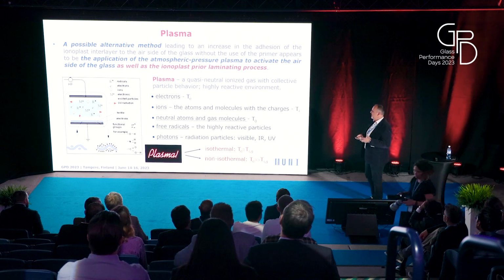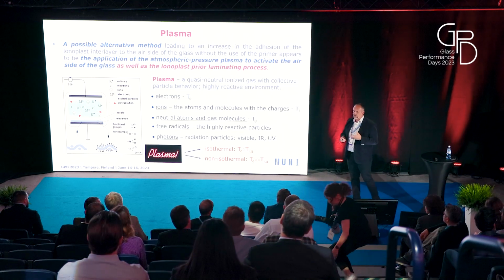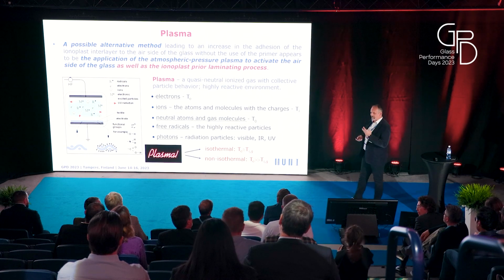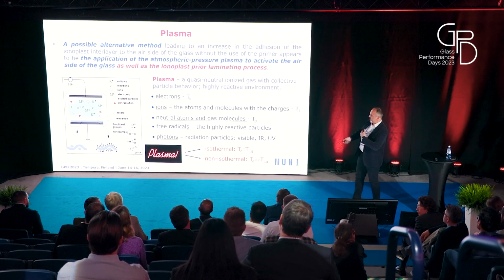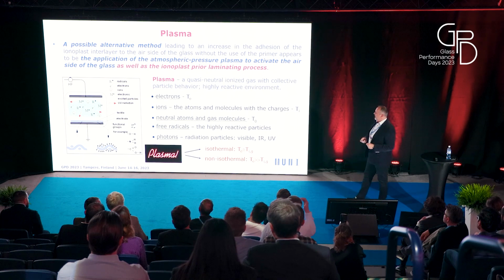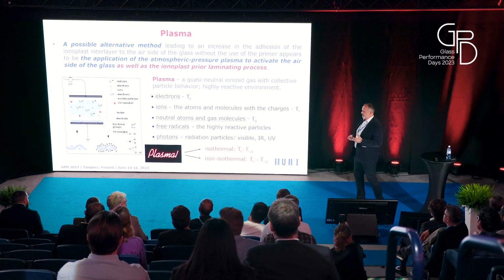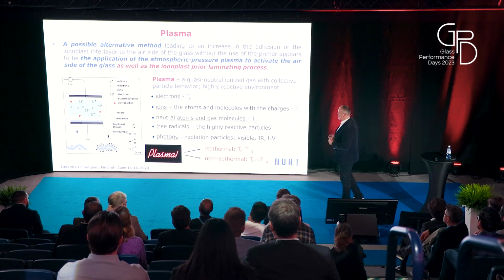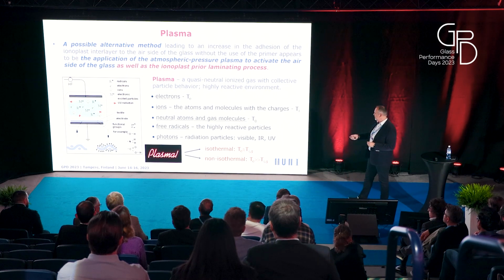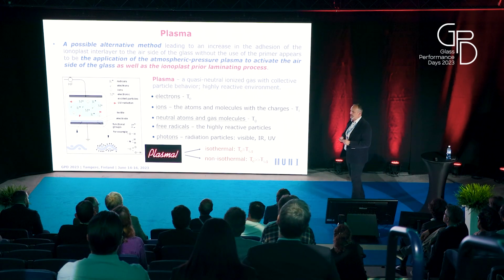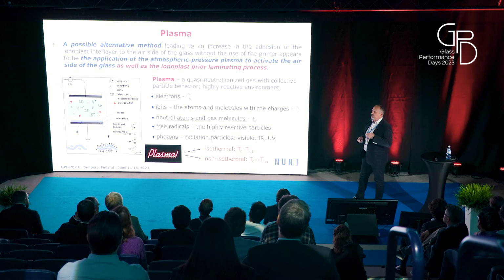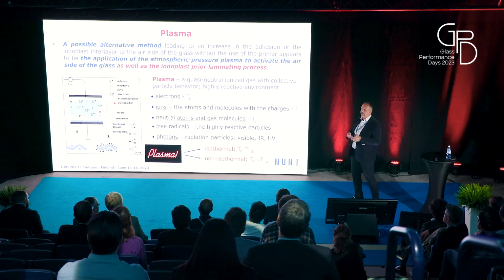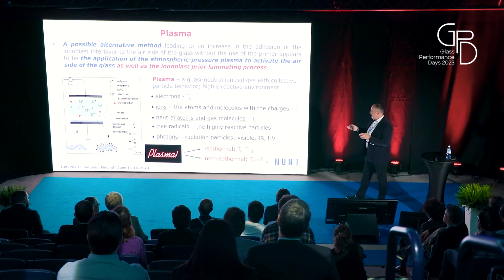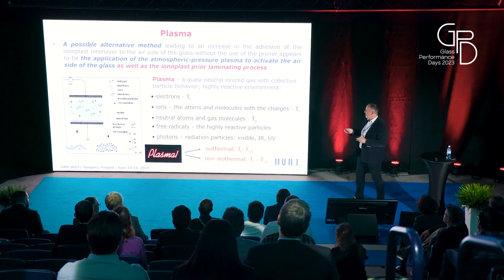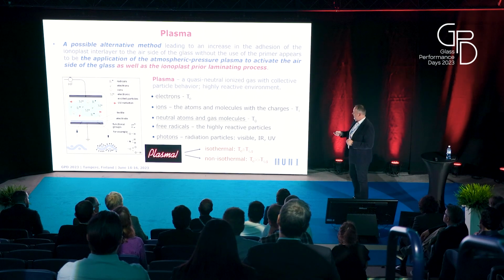Also, it is important to realize that plasma could have different properties. It is mainly generated by plasma discharges, as you can see on this picture on the left side. If the temperature of the very light particles, electrons, is much higher than the temperature of ions or gas, we are talking about non-isothermal or non-equilibrium plasma. Such a plasma is good for the surface treatment also of thermally sensitive materials. Isothermal plasma is the plasma where these temperatures are equal.